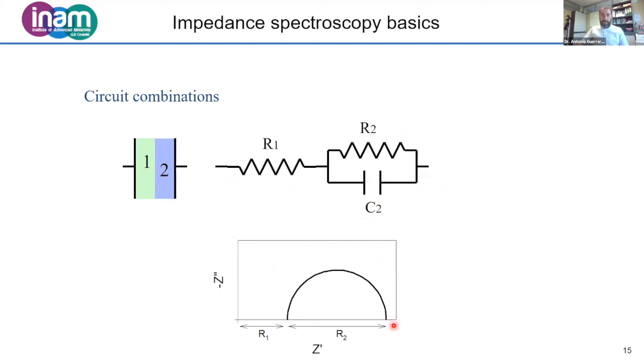And in the complex impedance plot, what you see is that there is a shift, R1, related to the conductor. This is the series resistance of a device that we measure by impedance spectroscopy. And this arc will be related to the properties of the semiconductor.